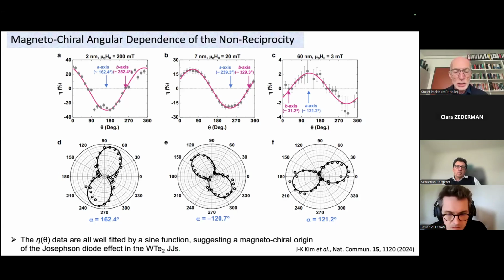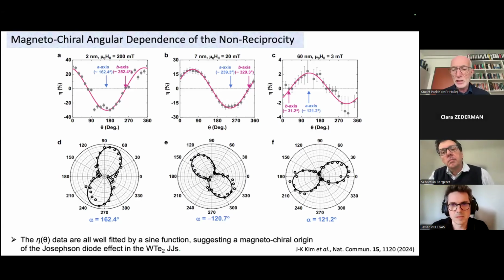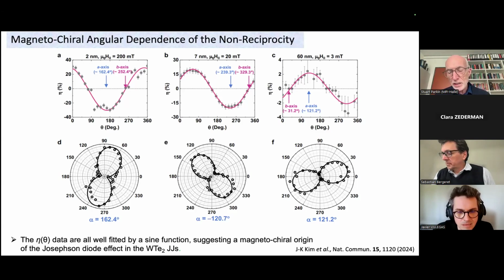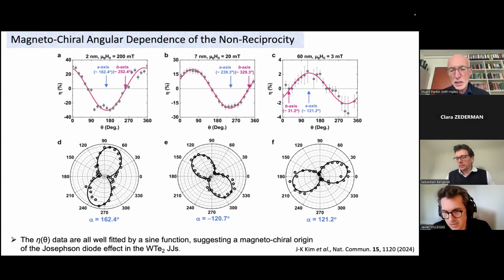And as I mentioned, we've got a vertical junction, so we can rotate the field always orthogonal to that current, but we can rotate it within the plane of the tungsten ditelluride. And what we find is then, afterwards, we can then determine the crystal orientation of the tungsten ditelluride. This is some collaboration with Georg Woltersdorf at the Martin Luther University. He has a polarized Raman system. So now we can determine the crystal orientation of each of these tungsten ditelluride flakes.